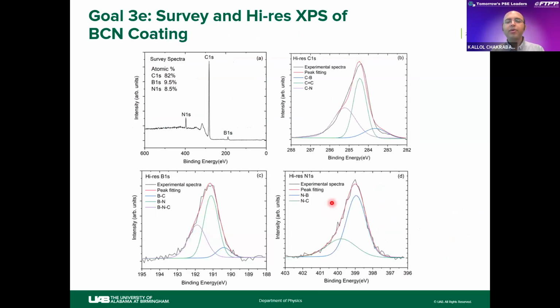So our next goal was to find the optimum conditions to synthesize this superhard material. We did this with optical emission spectroscopy. As I presented before, when we increase power and pressure, the C2 peak intensity increases. The C2 peak intensity is very important for synthesizing BC10N, because BC10N is a carbon-rich material, so we need more C2 in the plasma so it can be deposited on our substrate.